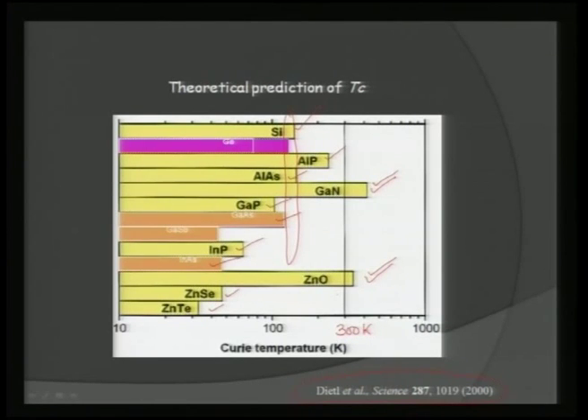Therefore, the target compounds studied in recent years are substituted gallium nitride materials and zinc oxide. There are also zinc chalcogenides — zinc telluride and zinc selenide — that show magnetic properties. Nevertheless, those around room temperature carry our attention. In the next few slides I will show research on several oxides and non-oxide compounds, and try to understand how to clearly distinguish between impurity-induced ferromagnetism and genuine intrinsic magnetism, looking at characterization facilities available to probe whether magnetic signatures are true or impurity-induced.